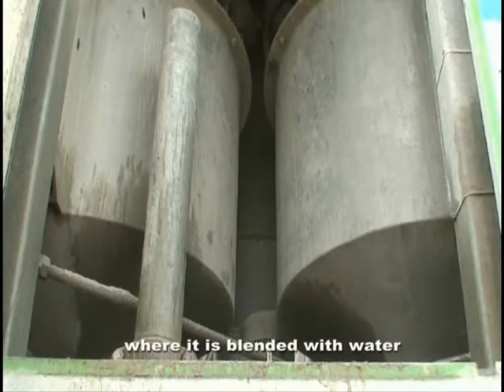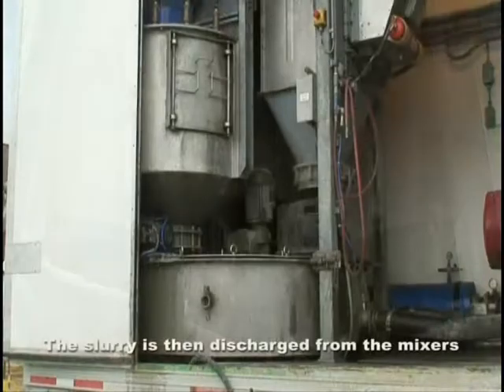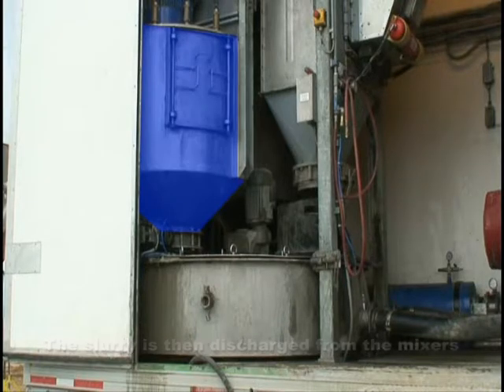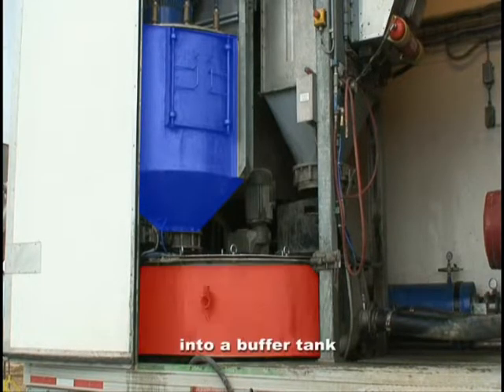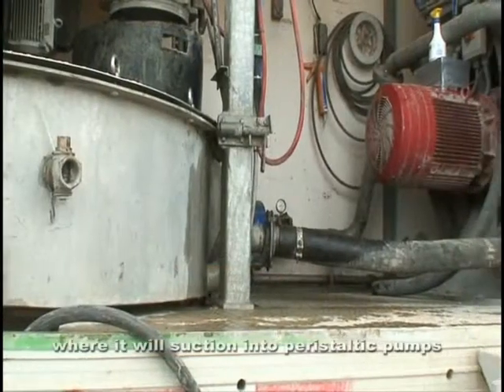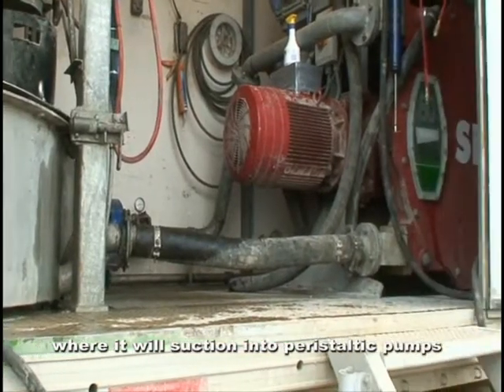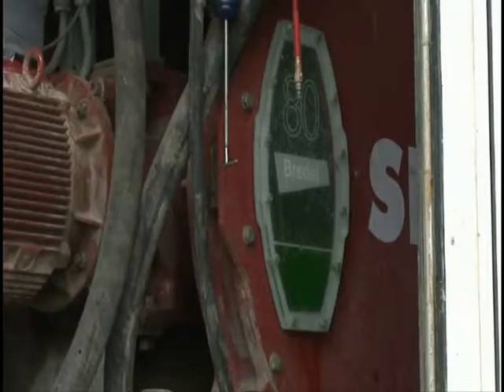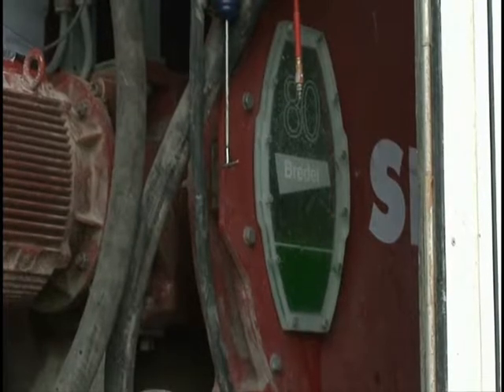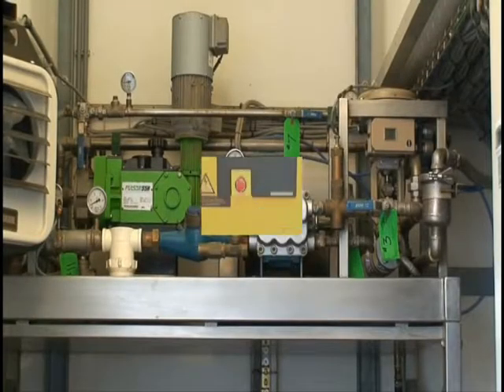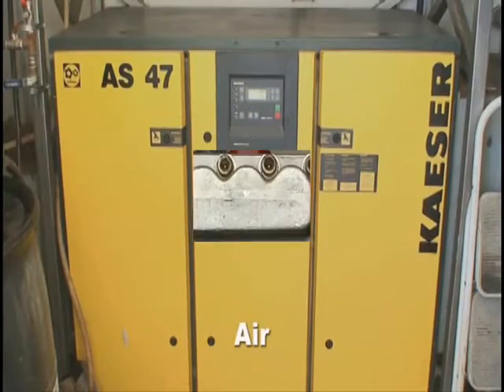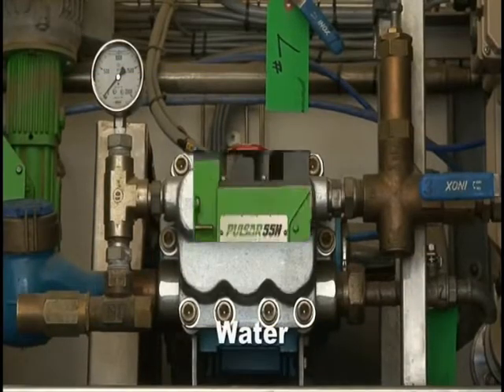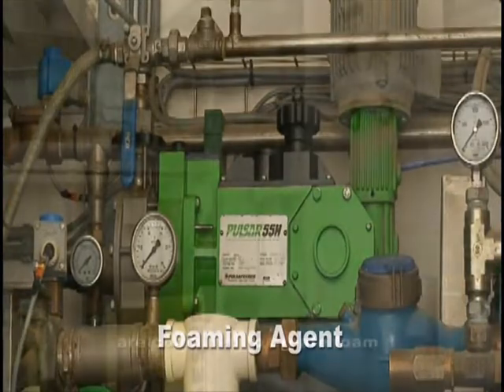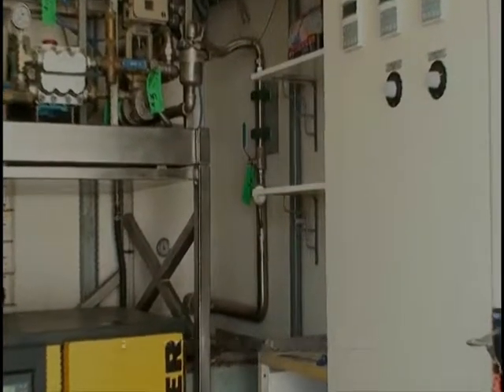The mixed cement and fly ash slurry is then discharged from the first mixing pod into a buffer tank, while the second mixing pod starts to produce a second batch. The slurry is then suctioned from the buffer tank by twin peristaltic pumps, which pump the slurry through the 3-inch discharge line. Meanwhile, preformed stable foam is produced by combining air, water, and foaming agent in a computer-controlled foam generator system. The foam is injected in line into the slurry, where it mixes under turbulent flow.